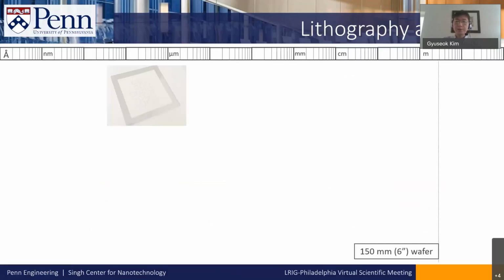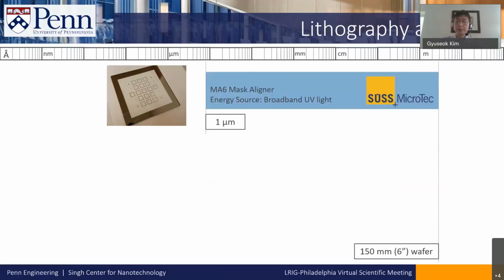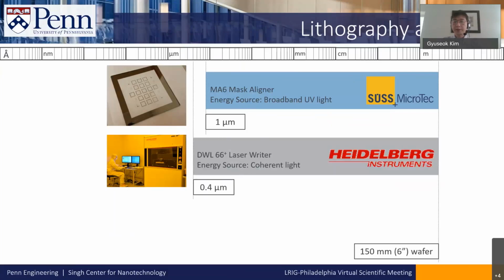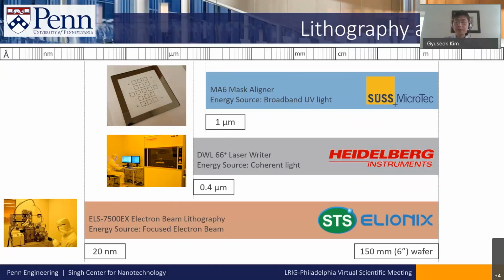At Penn, we provide tools with different wavelengths of light. You can use up to 6-inch wafers, and if you are targeting 1 micrometer feature size, you can use a mask aligner that uses broadband UV light. If you are targeting 0.4 micrometer feature size or greater, you can use direct write tools, which use a 365 nanometer specific laser wavelength for the exposure. If you are targeting an even smaller feature size, you can make up to 20 nanometer features with the electron beam lithography tool.